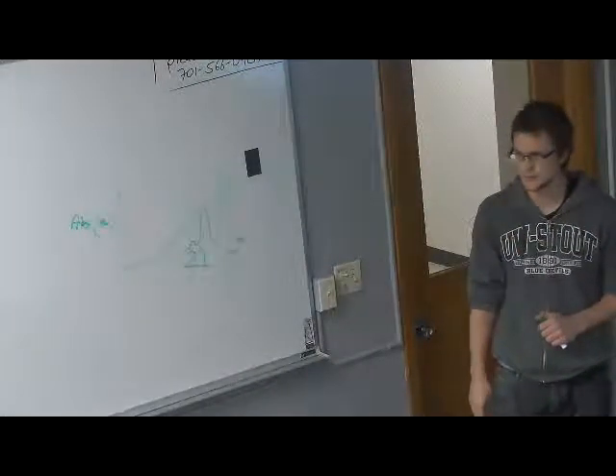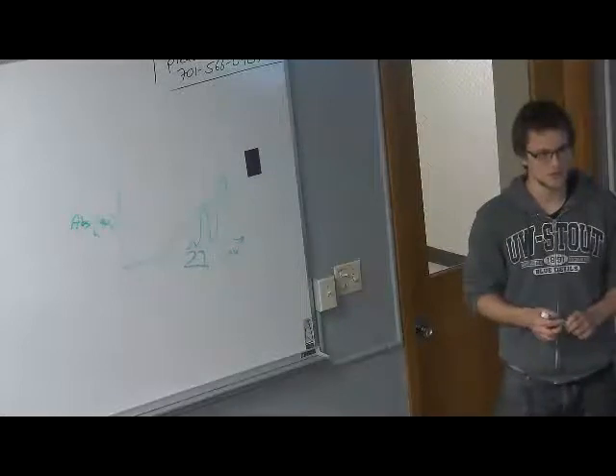around 3, I think. Because it's a small dot, you expect it to follow the quantity, so the confinement size effect should be much stronger. But the size of your quantum dot is much smaller compared to what you really synthesize, right? Right, so it should be a big blue shift for this one, and that's why they come to agree with your 2.2. And it just happens to be a 0.5 eV plus.